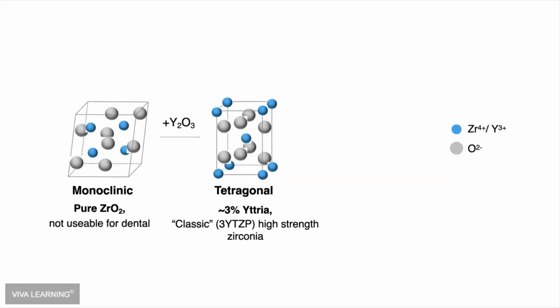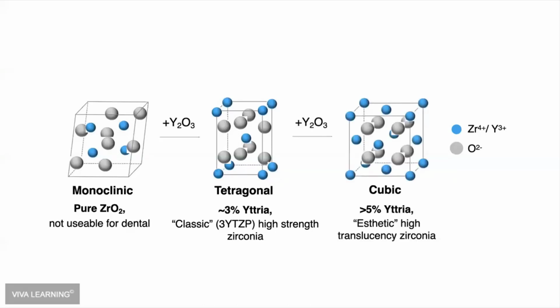And it was a very, very opaque, almost, I will call it ugly form of zirconia, but super strong, like 1200 megapascals, that first came out to the market, at least for same day. I would take the crowns and I would put them on a wood table. I would hammer it. The crown wouldn't break, but I would see the imprint of that margin in that wooden table. That's how strong this material was. Those materials have actually been taken off the market because of the materials that are now coming onto the market.